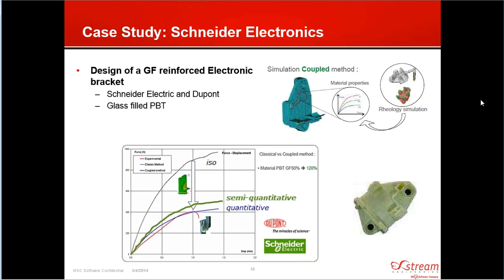And what you see is that the semi-quantitative approach gives them a big increase in accuracy right away by taking into account those local fiber orientations, and that's really pulling the material model right from the database. And then the quantitative approach is going to bring them even closer and a much higher level of accuracy by tuning that material model to some material test data that they had before this analysis.